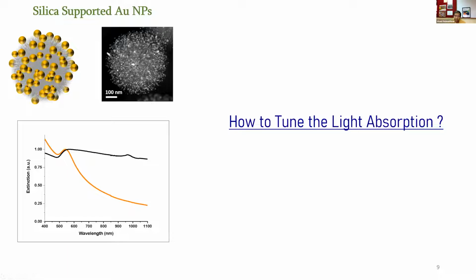What we really wanted, if we want to develop a good photocatalyst, then the first condition is that it should absorb a large number of photons at all the wavelengths. So some sort of broadband light absorption that we needed from visible to near IR. The question is, how do I tune the light absorption? There is a concept that if I can tune the distances between the gold nanoparticles, then the electron clouds of these gold nanoparticles couple with each other, known as plasmonic coupling, and that plasmonic coupling allows you to have a broadband light absorption.